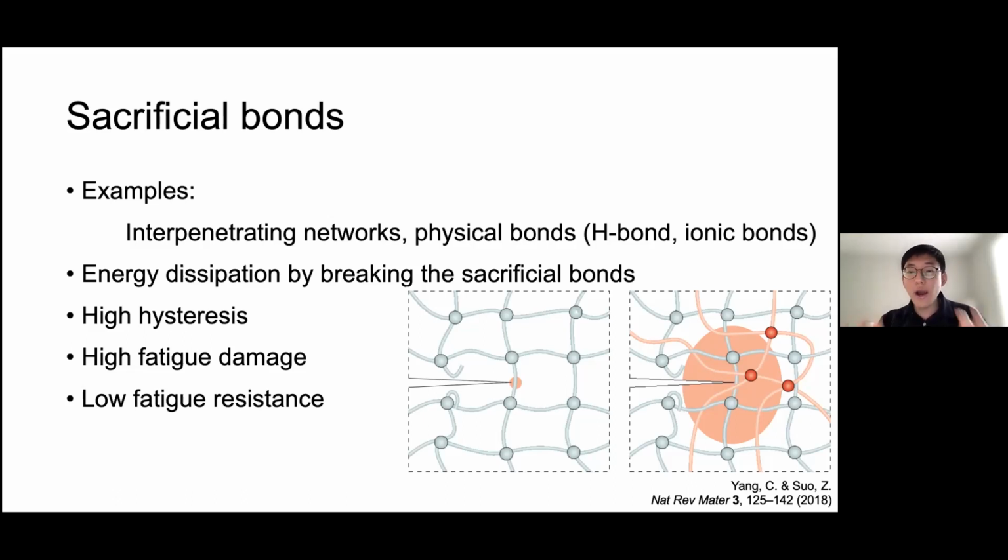The reason why these materials are inelastic is because this toughening and stiffening mechanism relies on inelastic dissipating mechanisms. So before our paper, people believed that if you want to increase the toughness, you need to increase the area between the loading and unloading curve so that you increase the amount of hysteresis.